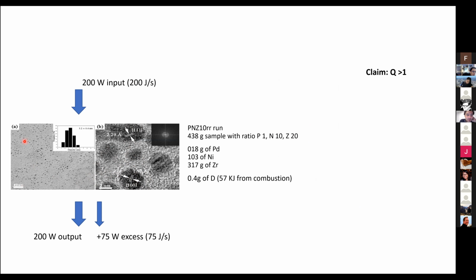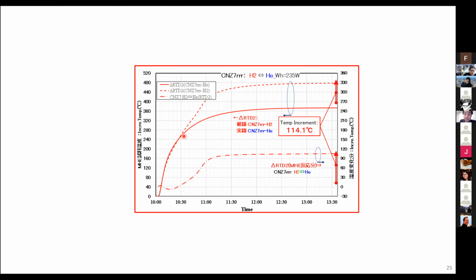So you have a zirconium matrix, a zirconium structure, and then in these you have little raisins in a cookie. You have these palladium nanoparticles sitting there, and there's a rationale for that. We can talk about that more if you like, but there are certain sites in the nanoparticles in that kind of configuration that may be particularly suitable for fusion. If you're interested, we can talk more about that. But their results are the following.